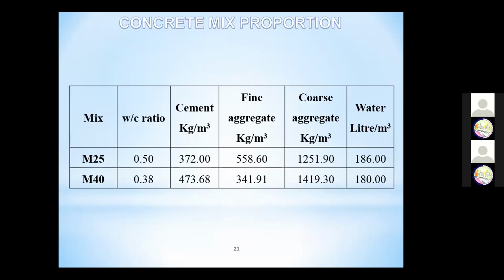Now some concrete mix designs. For the M25 grade, 0.5 is the water cement ratio, cement 372 kg per meter cube, fine aggregate 558 kg per meter cube, same way the coarse aggregate, and same way in the M40 grade, 0.38, cement 473.68, and some other fine aggregate, coarse aggregate, and water. So this is my design mix based on the design mix code and the standards, the material properties